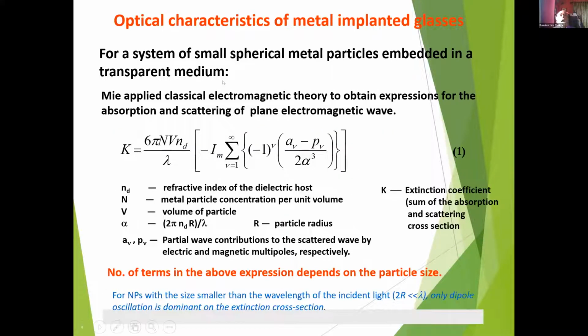This is the absorption coefficient or extinction coefficient that we have calculated by applying the Mie theory of electromagnetic radiation interacting with metal particles in some host material. Then the extinction coefficient is 6 pi, etc., where n is the number density of the metal particles, v is the volume of each particle, nd is the refractive index of the host, here the glass, lambda is the wavelength of the incident light, and a nu and p nu are the partial wave contributions to the scattered wave by electric and magnetic multipoles.